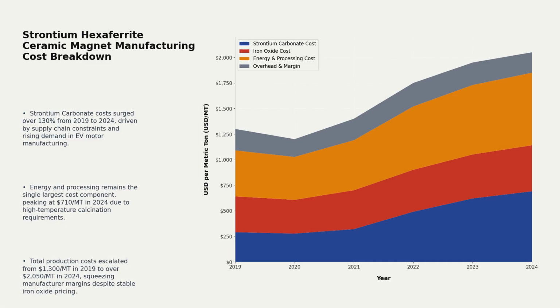The upstream chemical deficit is propagating directly down the industrial supply chain. Strontium carbonate is synthesized with iron oxide to produce strontium hexaferrite ceramic magnets. The raw material cost contribution of strontium carbonate to these finished magnets has risen from 22.3% in 2019 to 33.7% in 2024. This has driven a 57.7% escalation in total magnet manufacturing costs. Total costs rose from $1,300 per metric ton to $2,050 per metric ton over the 5-year period. Energy and processing costs also rose by 57.8%, compounding the raw material shock.